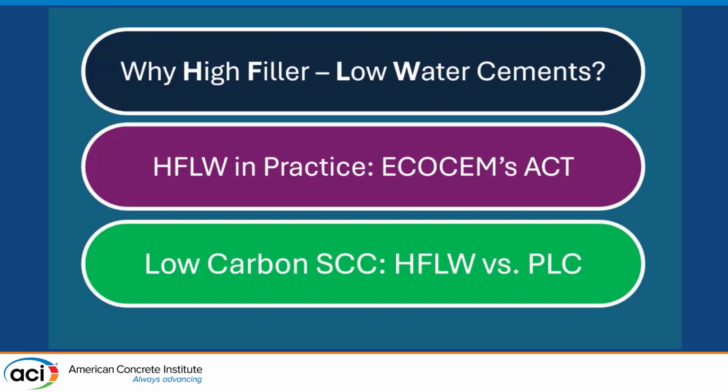About 25 years ago, more than 25 years ago, in my PhD thesis, we were using a lot of limestone powder, and we were also checking the heat of hydration. Absolutely, there should be no problem. It's much better because limestone powder is relatively inert, right? So the amount of heat generated is less than that of cement. So that's good. Can I have a question?